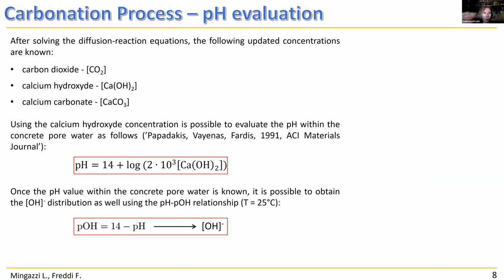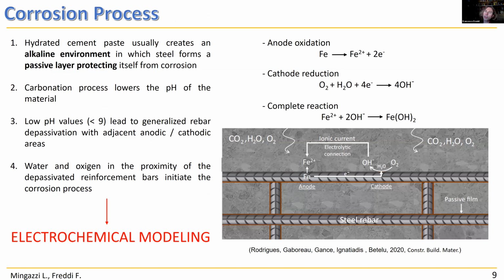From the concentration of the previous elements, in particular from the concentration of calcium hydroxide, it is possible to determine the pH of the element, and with a basically simple relationship with the pOH, it is possible to determine the pOH and the concentration of the OH- ion, because these are crucial elements for the corrosion process. In fact, usually, due to the alkaline environment, the bars are passivated, so the corrosion phenomenon is very, very, very slow. But the carbonation process strongly reduces the pH value. And for values of pH smaller than 9, there is a depassivation with the creation of adjacent anodic and cathodic elements, and a creation of a current from the anode to the cathode.